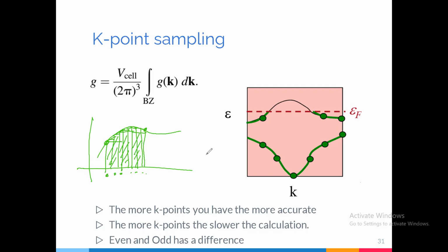So this is what the K-point grid is about. And the K-point grid you give in the XYZ, so you give like 2 by 2 by 2 or 4 by 4 by 4, if your crystal axes, A1, A2, A3, are of the same length. So for simple cubic, we know that it's the same length for simple cubic crystal systems, right? Therefore, you can go with 4 by 4 by 4 or 2 by 2 by 2. You can also do odd numbers, and I know VASP has a different accuracy for odd and even numbers. They recommend some, I forget now, but if you read their manual, the VASP software has a different guideline. But it doesn't matter. You can have this particular K-point grid convergence by just changing these numbers and seeing how the energy converges, similar to the one that we ran for the energy cutoff.